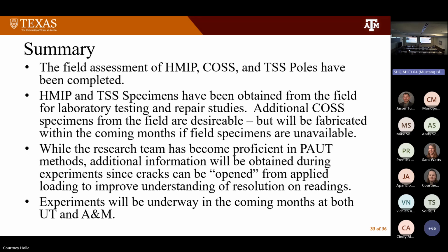We actually think, though, that we're going to get better at this as we start getting in the laboratory, because what's nice about the laboratory is we can go in and say, okay, here's where we're finding cracks, and here's where we think the cracks end. When we actually put them into a setup, we can see, is that really what happens? Because when we pull up on them, it tends to open the crack and it becomes a lot more visible with the inspection technique.